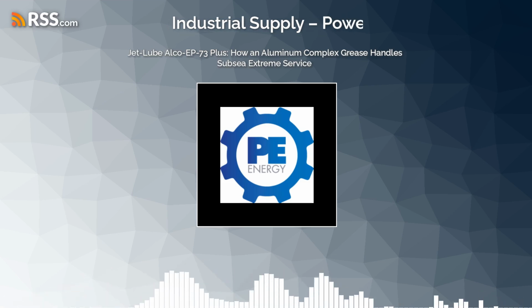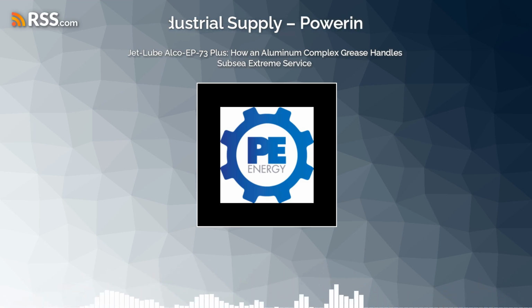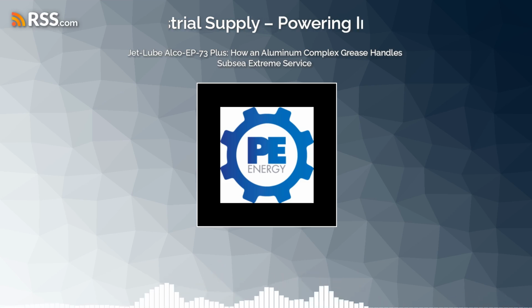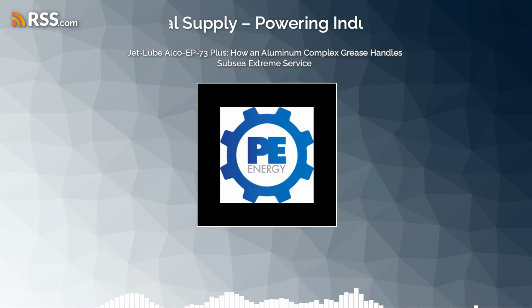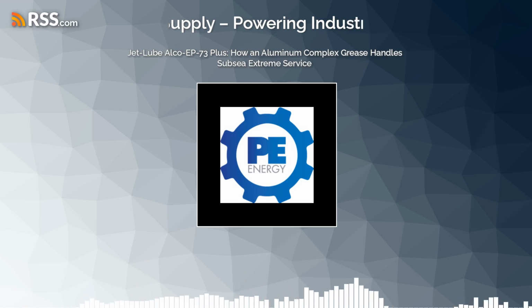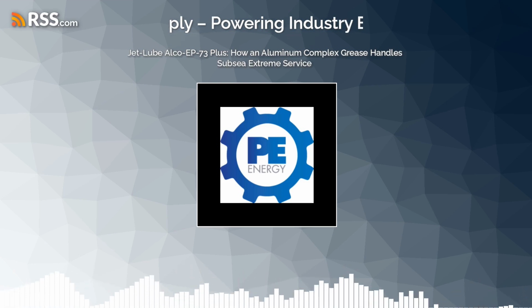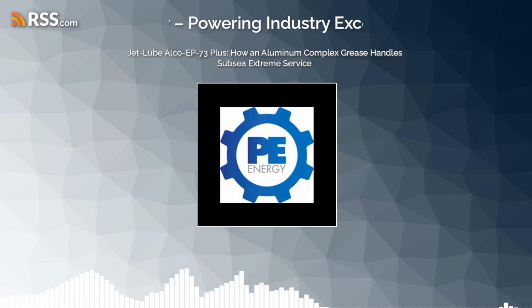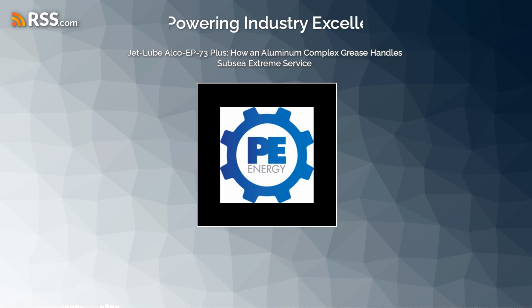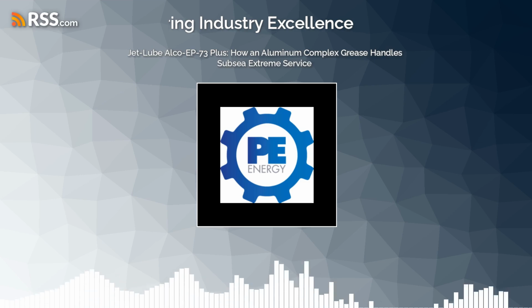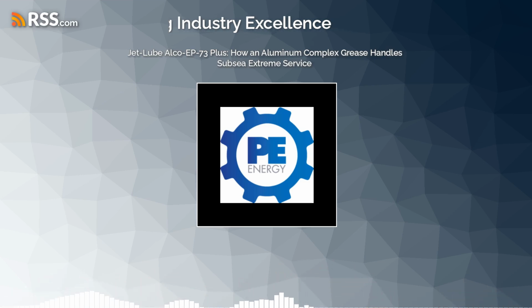It really is. And the wear scar diameter of 0.7. That means the physical damage to the balls under typical testing loads leading up to the weld point was less than a millimeter wide. That 0.7 millimeter scar is the physical proof that the organic additives are doing their job. Even when subjected to violent spinning and crushing pressure, the chemical barrier prevents all but a microscopic fraction of a millimeter of physical damage to the steel.